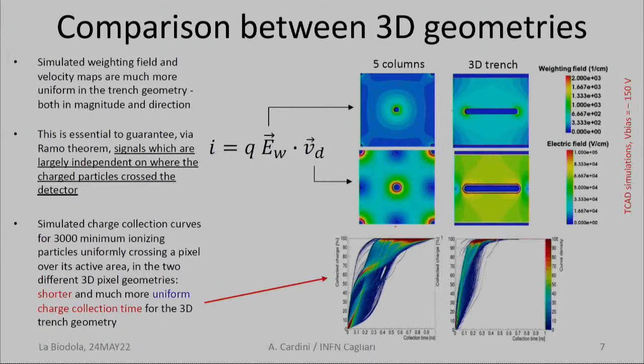If you look at this solution at the simulation level and compare it with the traditional columnar design, you see that the weighting field and the velocity map are much different from a square columnar 3D design versus a trench design. In the two components, those are much more uniform with respect to the columnar case.